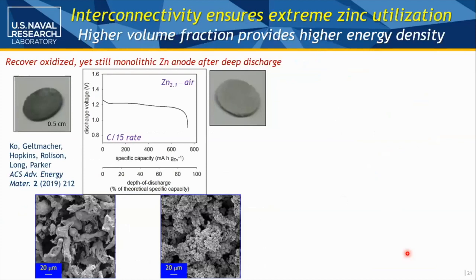And currently those start-stop microhybrids maybe last a year, even though they're rated for two. And again, sponge goes in, sponge comes out. So often we change things. The original science work was done with 20% of the sponge being zinc. And for an energy density normalization, that's not enough zinc. So new postdoc from Joe Parker's original work in the science paper, Jesse Ko came in and kicked it up to 2.1 grams of zinc per cc of sponge. Joe was working with 1.4. And you just do a zinc air just to show you can eat most of the zinc.